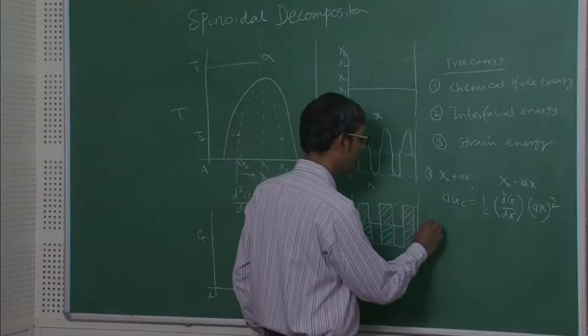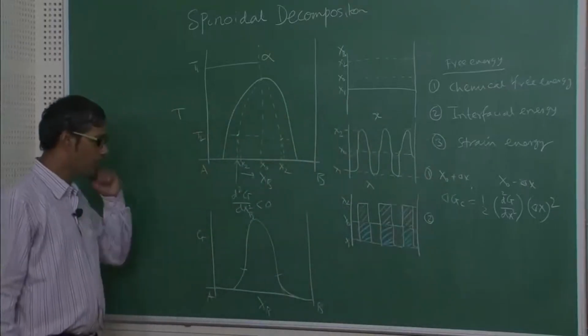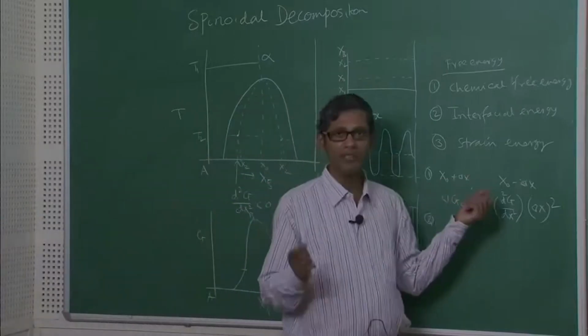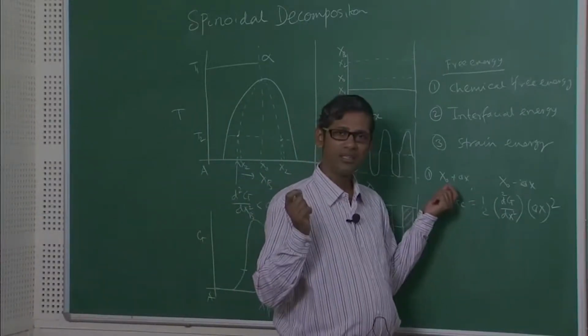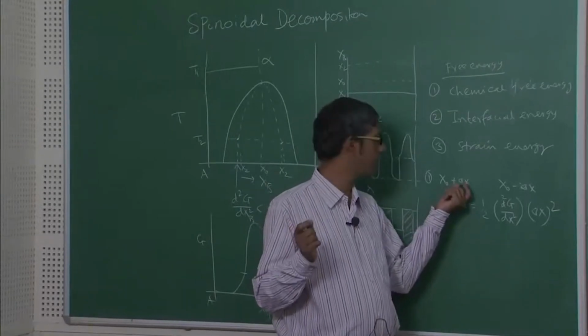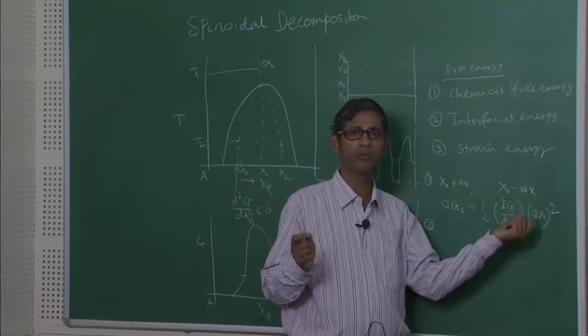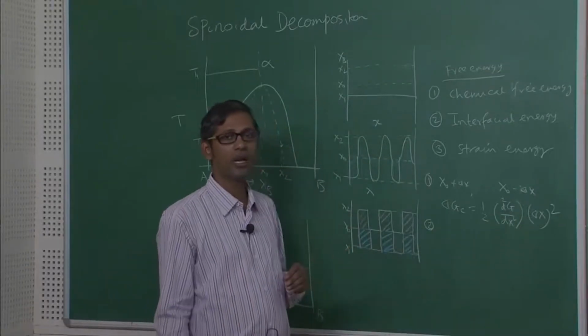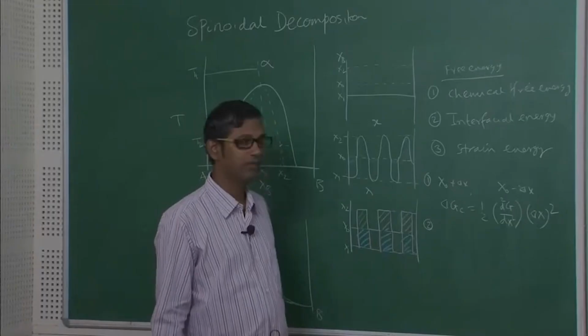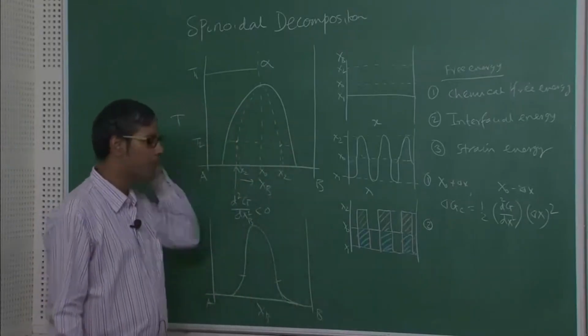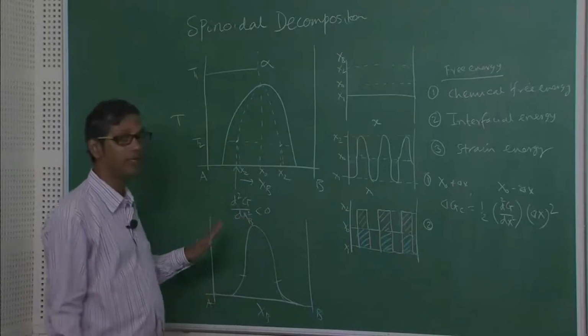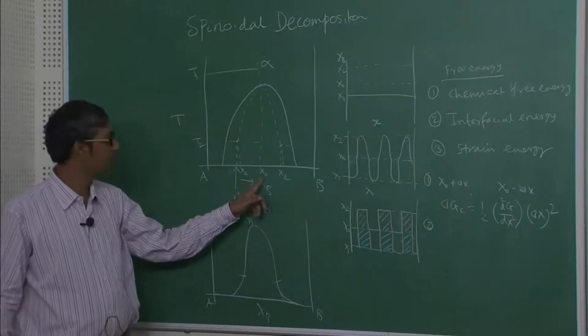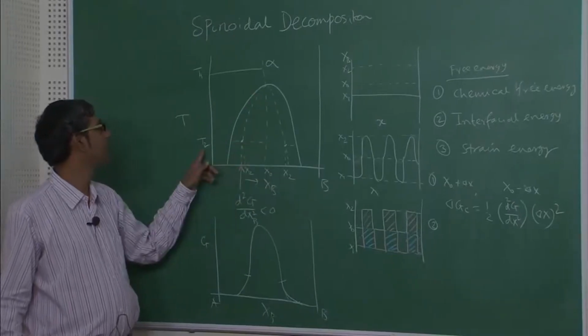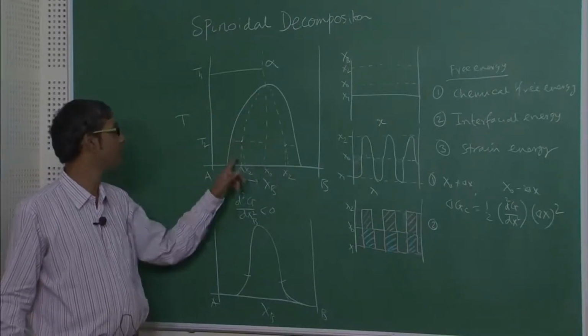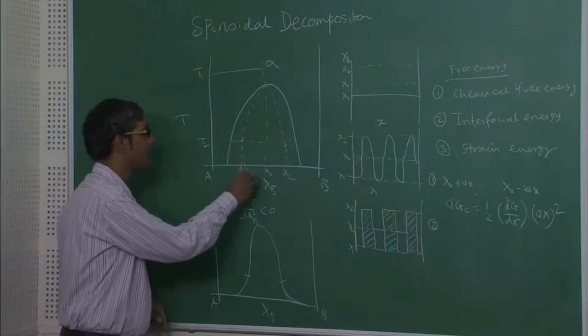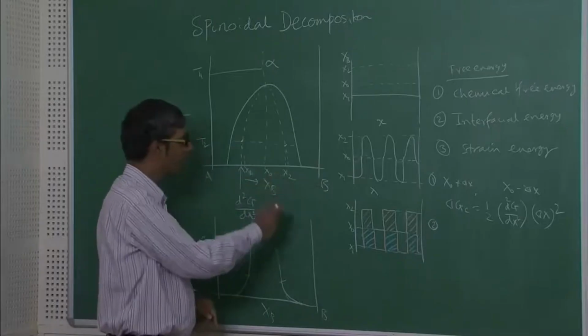Now, what is the interfacial free energy part? Well, as you know, at the beginning when the compositional fluctuation is very small, that means you have regions which are rich in some element by a very small amount, lean in some element by a very small amount, finely dispersed. So, what will happen? There are going to be interfacial energies because of that. What is the origin of that? It is very simple. This system is basically a cluster based system. Why? As you know, if I have a homogeneous alloy composition X0, as it is quenched at temperature T2 from T1, it is decomposing into two phases with compositions X1 and X2, right. So, X1 is A rich, X2 is B rich as compared to X0.